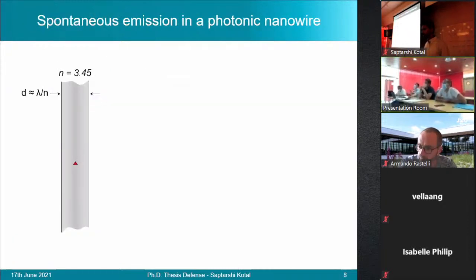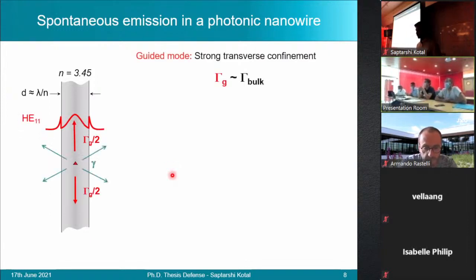Now, photonic nanowires are a kind of waveguide which are very similar to optical fibers. In particular, we have a cylinder made of gallium arsenide, which has a diameter of the order of 1 wavelength in the material. At this diameter scale, of course, the waveguide confines the guided mode strongly in the two transverse directions, making it possible to achieve a spontaneous emission rate which is very close to that of the bulk.